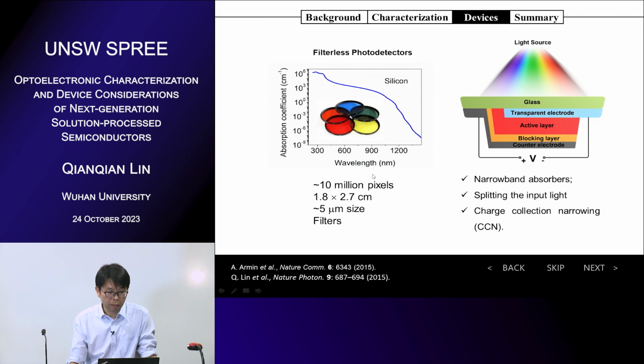So normally you use a lot of filters, and the size of the silicon detectors nowadays is very small, normally around a few micrometers, and you have 5 or 10 million pixels in an array. So you have to put a lot of filters in front of the photodiodes, and it should have very good, matched fabrication. But if it's not matched very well, then you will lose a lot of resolution. So our idea is to reduce the usage of filters.